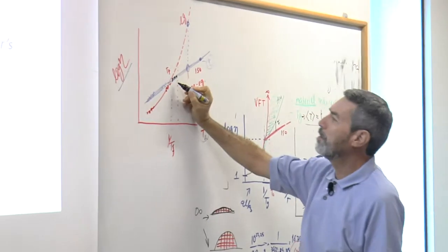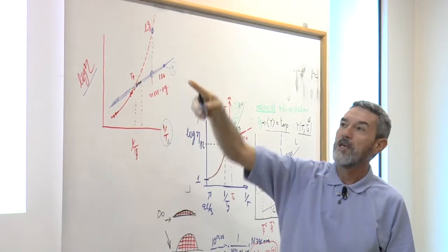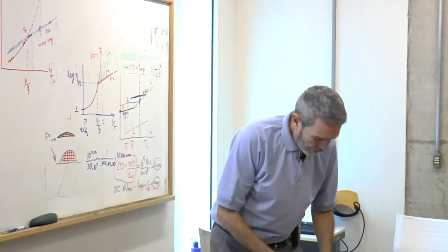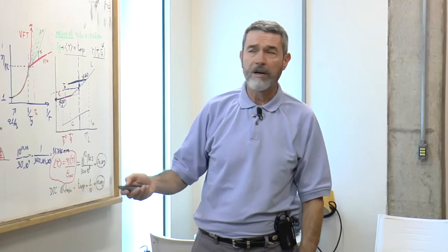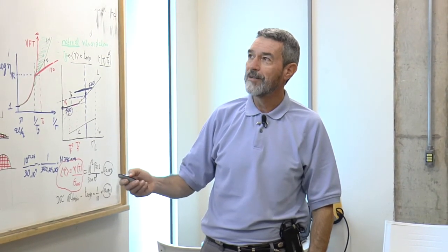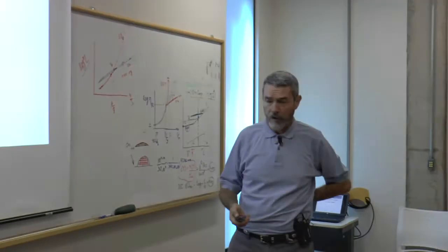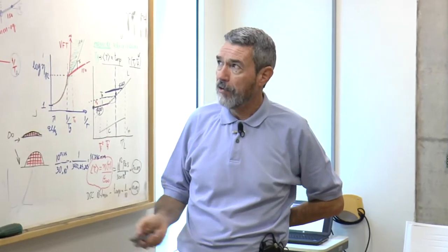Mazurin had a few, 2 or 3 data points of isostructural viscosity, using the Adam-Gibbs model to be able to extrapolate here down to room temperature, 30 or 25 degrees Celsius. And the final result is 10 to the 24 years. Not as high as 10 to the 32 years that we had for GeO2, but still very, very long. Very, very long. Now, many people have worked and done other calculations on the viscous flow of medieval cathedral glasses.